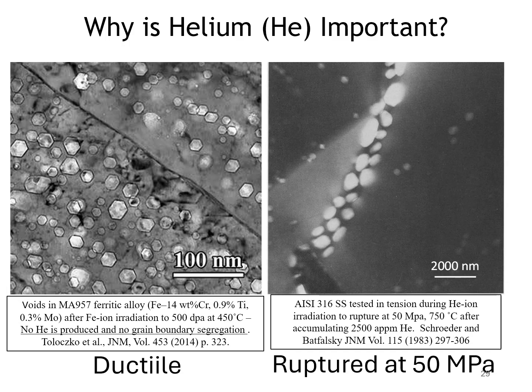So why is helium important? Here are two slides. This one is an irradiated sample, 500 dpa. What that means is every atom has been displaced 500 times at this point. You displace enough atoms that some of the vacancies created will form clusters and increase the porosity of the material, just like when you bake a loaf of bread and it rises. But the grain boundaries are generally pretty clean, and that's because there's no helium involved.